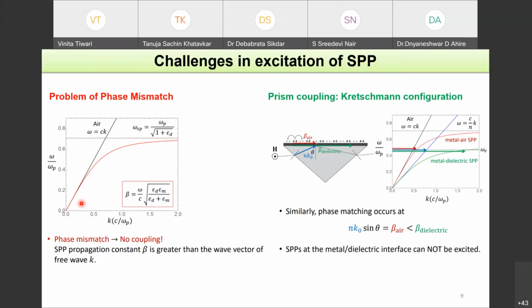So what you can do is use a geometry called the Kretschmann configuration, like this. This is your metallic film, and you place the metallic film on top of a glass prism, and you shine light from the glass side. Because of the dielectric permittivity of the glass, you can reduce the slope of this black line to this blue line. We all know that omega equals ck is the dispersion relation of a photon in vacuum or air, and when it goes inside any material with refractive index n, it becomes omega equals c by n times k. So the slope basically reduces, and this blue line is the new dispersion relation of a photon in this glass prism.